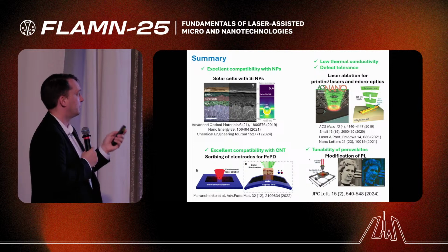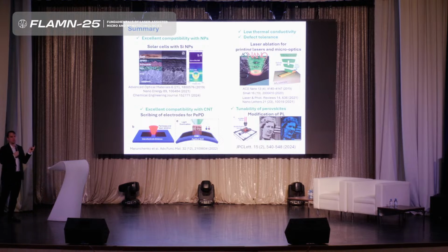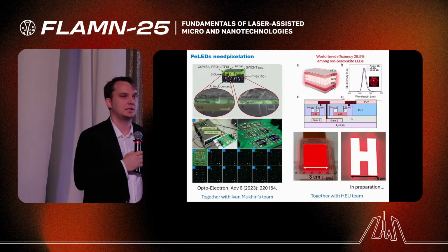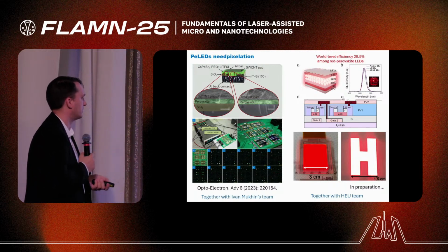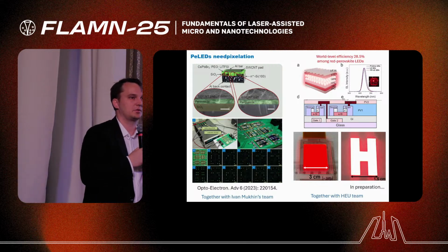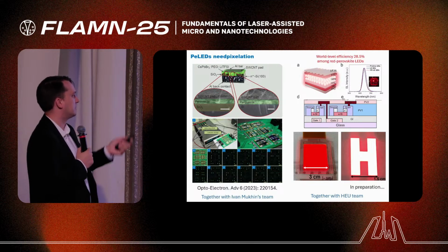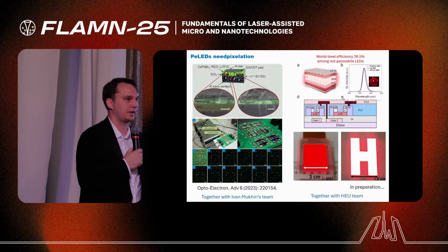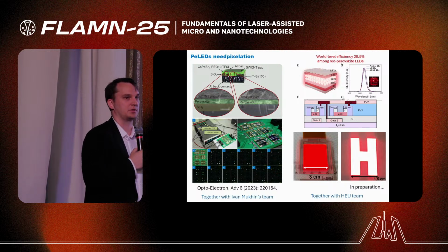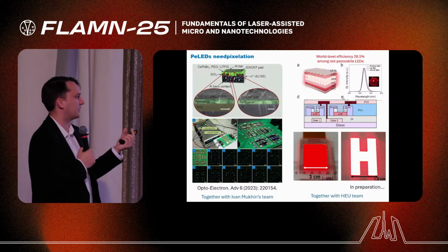So here I would like to overview our recent results. If we use laser ablation for non-perovskite materials, we can apply them for perovskite solar cells and photodetectors, and if we directly process perovskites by laser, we can create micro lasers, nano lasers, and do some encryption in perovskites. Also, as an outlook, we are now actively working on perovskite LEDs. This is work in our lab in collaboration with a university team from Munich. They provide us nice substrates, and we created a pixelated display based on perovskites in the green range. In this case, each pixel size was just more than 100 micrometers.